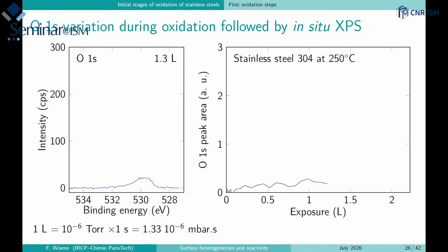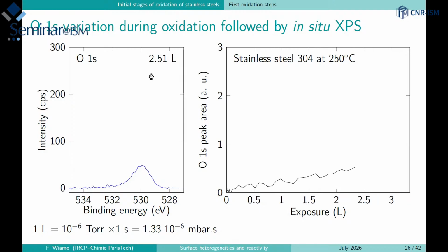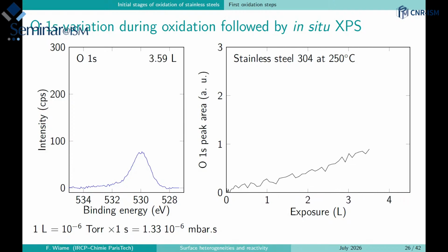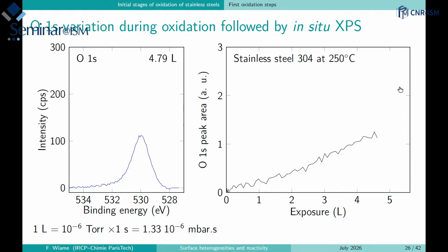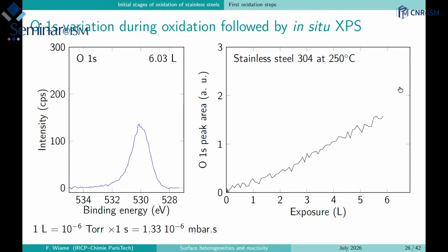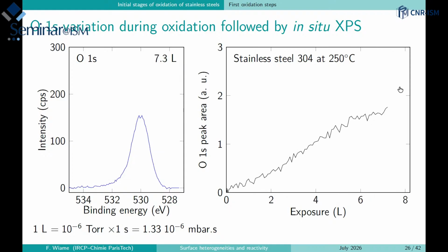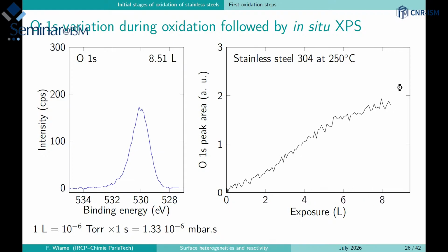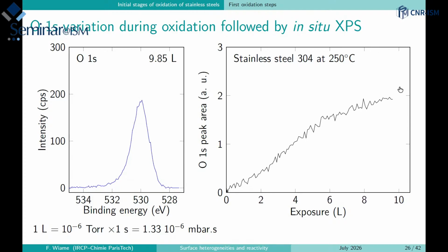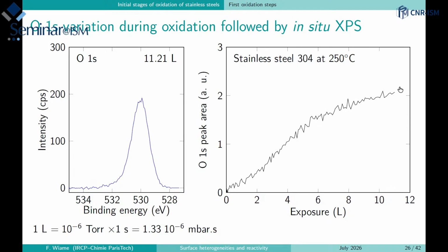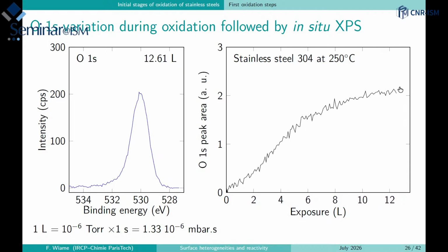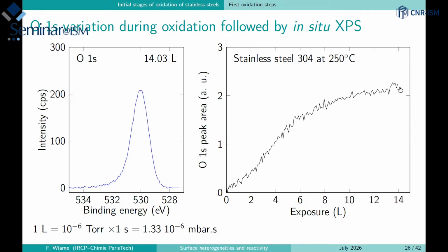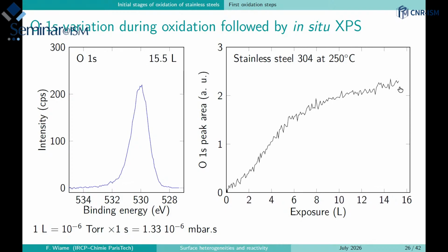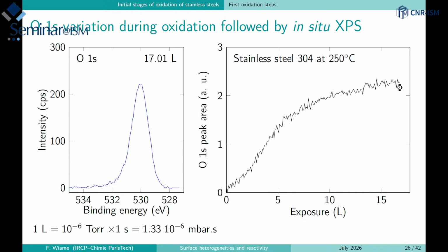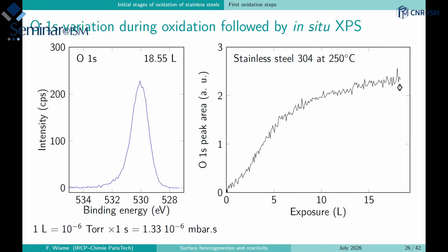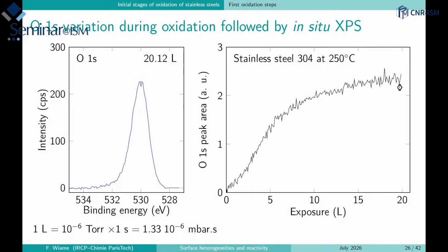And this is the spectrum. We have one spectrum which is measured every 10 seconds. So we can integrate the area of the oxygen 1s to draw the kinetics of oxidation of the material. And you can see that this is quite fast. In a few Langmuir, you already have some kind of saturation. A few Langmuir corresponds roughly to a few nanoseconds at atmospheric pressure. So that means that this nanometric oxide layer is formed quite fast. Here you see that at 15 Langmuir, in the case of stainless steel at 250 degrees Celsius, we have already almost saturated the reaction at the surface.